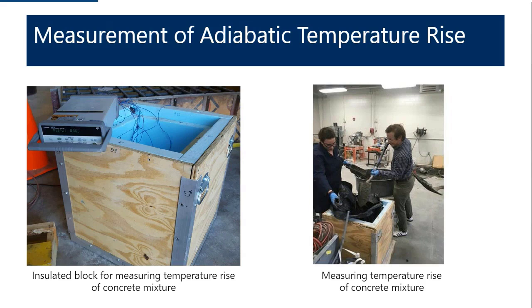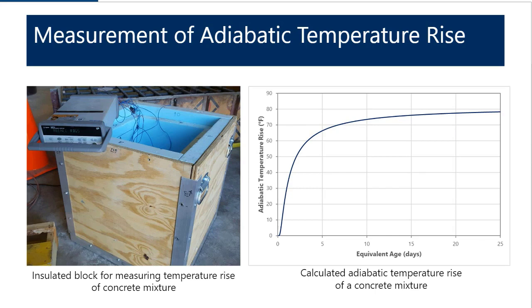One of the ways that we can also enhance a thermal control plan and enhance our understanding of mass concrete behavior is by measuring the adiabatic temperature rise of a concrete mixture. Now, the adiabatic temperature rise is sort of like a heat signature of a concrete mixture. Basically, it's how much heat can be generated, or how much temperature rise can be generated, by a concrete mixture based on its total amount of cement, its SCMs, and the particular ones that are being used for a project. And we measure this in the lab using a large insulated block called a semi-adiabatic calorimeter. You can place the concrete into this well-insulated block, measure the temperature rise, and use that to understand how that concrete mixture is going to increase in temperature over time. So for this particular concrete mixture that I'm showing in the graph here, this mixture has a total adiabatic temperature rise of about 80 degrees.